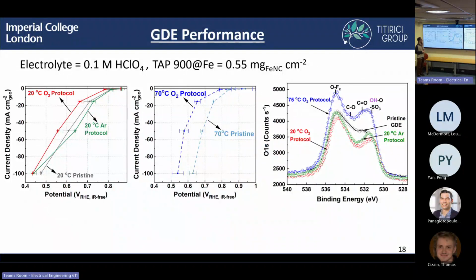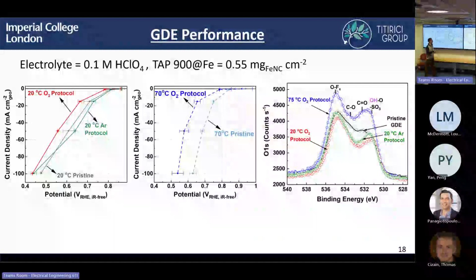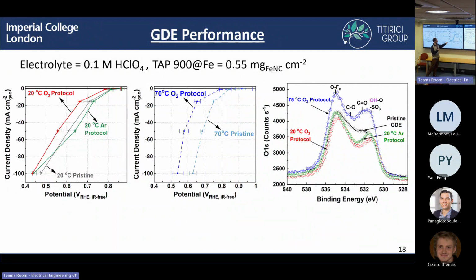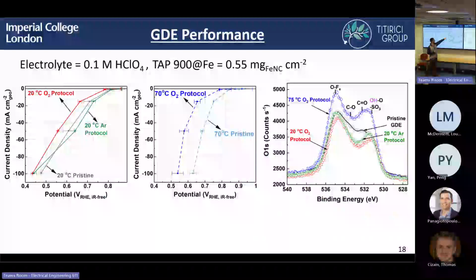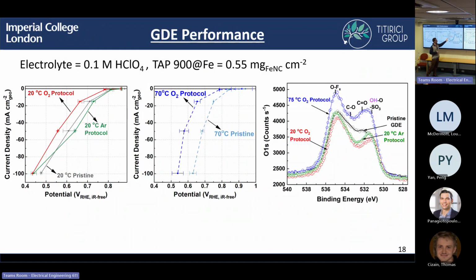And so if we look at XPS, we can see some clear differences in the pristine material compared to the 75 degrees protocol. We see there's an increase in the amount of oxygen surface functional groups, whereas in the argon and oxygen at 20 degrees, we don't see any clear difference or a less significant difference to pristine material, suggesting that it's only after the AST at 75 degrees that we have some surface oxidation, which can limit or change the turnover frequency of the catalyst, whereas at room temperature, we don't seem to see any surface oxidation. So the degradation under 20 degrees should just be coming from iron dissolution, we propose.